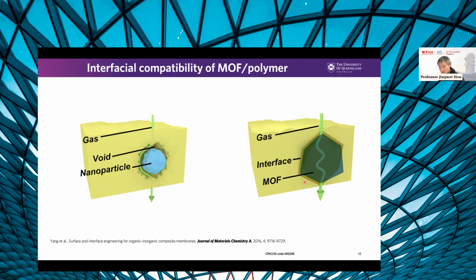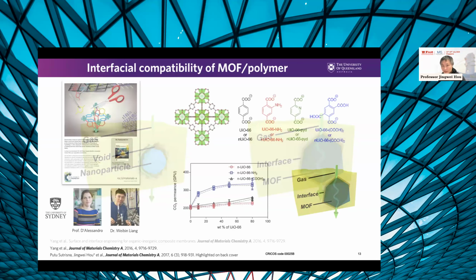We can actually functionalize the MOF. We can actually use the MOF polymer. Say we put organic polymer chains on top of the MOF, which can even participate in the polymerization of the polymer membrane itself. But in this case, we're actually creating a more rigid, more robust interface between two materials that can slow down the mass diffusion within the membrane. So this seems like a very fine balance between two sides of the huge issue. So how can we solve that?